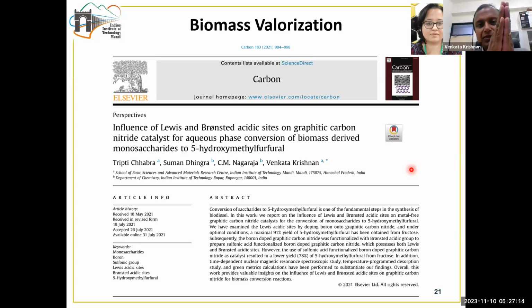So, in this work, what we have done is we have taken graphitic carbon nitride and doped certain elements of the graphitic carbon nitride using boron, which is a heteroatom that induces the Lewis acidic nature in the catalyst. Subsequently, we functionalized this boron-doped graphitic carbon nitride using sulfonic acid groups. When we functionalize these groups, it has both these acidic properties. One is the Lewis acidic nature, which is brought about by the boron doping, and the sulfonic functionalization brings the Bronsted acidic nature onto this catalyst. So the single catalyst has both these acidic natures, but they didn't work synergistically. Nevertheless, we were able to decipher why it is not working and eventually got this work published in Carbon in 2021.